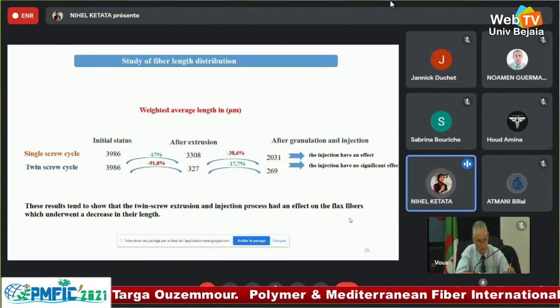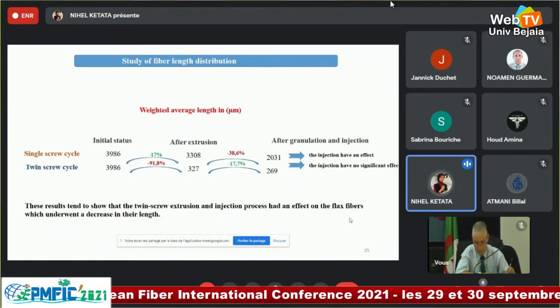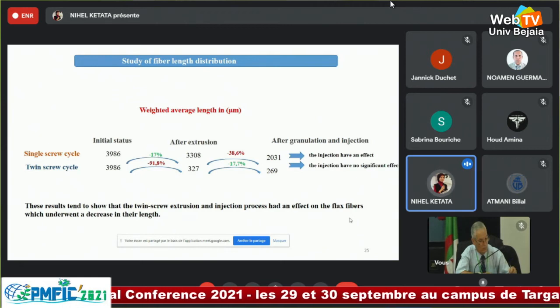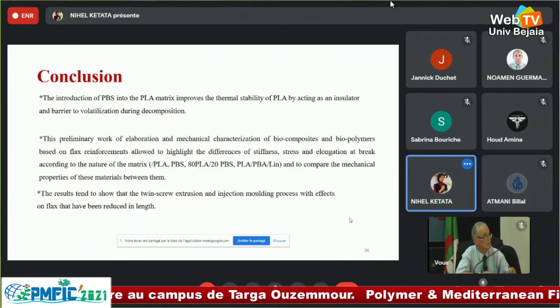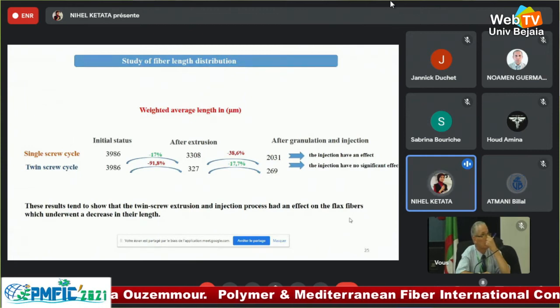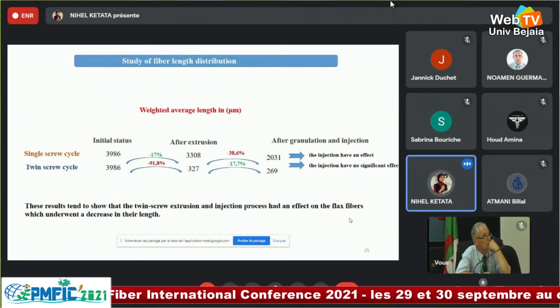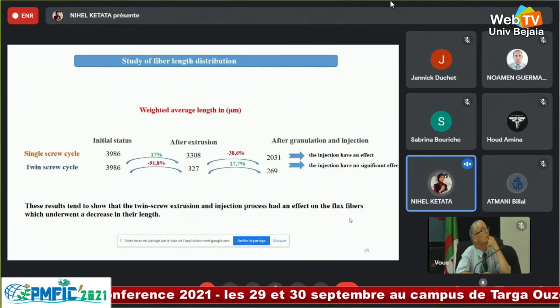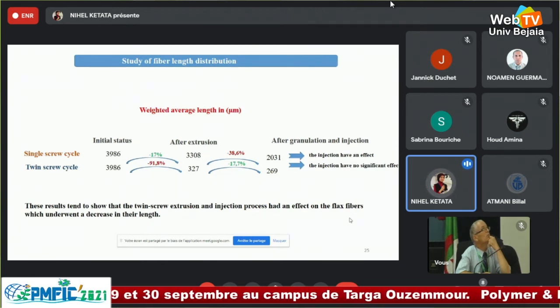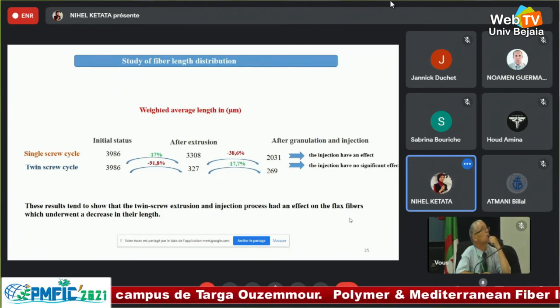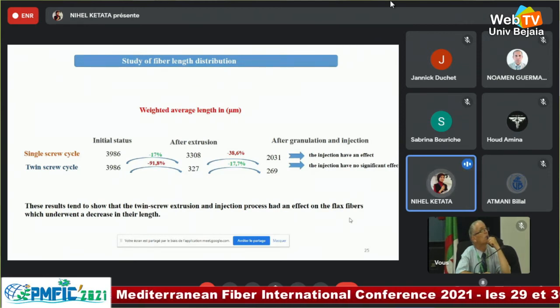So this study showed a reduction in the average length, and it is totally observed that the injection results in a reduction in fiber length in all the polymers. These results tend to show that the twin-screw extrusion and the injection process have an effect on the flax fiber, which underwent a decrease in their length. The injection has an effect on the fiber length distribution in the samples obtained by the single-screw extrusion. On the other hand, for the twin-screw cycle, the injection has no effect.